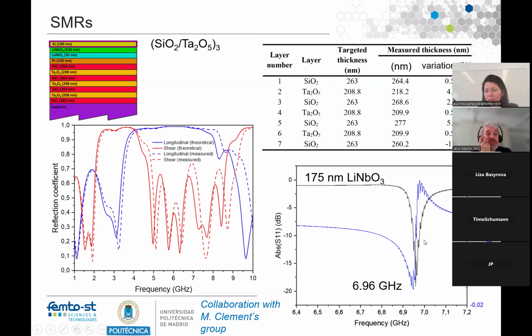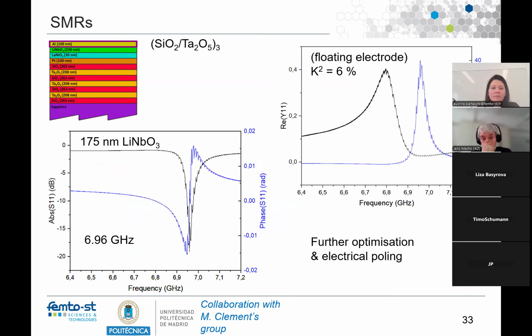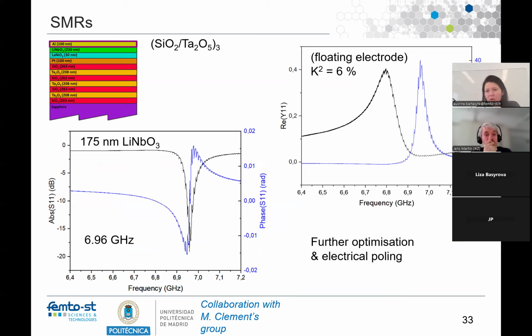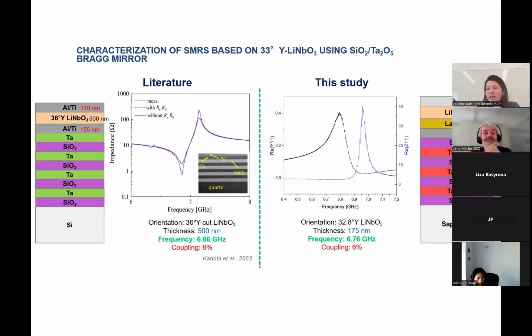And then we see these small ripples on the side. So the mirror is probably not working perfectly, but we had a nice resonance at 7 gigahertz. Then we used just a floating electrode and measured a coupling of about 6%, more or less. The signal is maybe a little bit noisy. To compare if it's good or bad, the only reference I have is again from the Kadota group. We did a very similar mirror, not tantalum oxide but tantalum silicon dioxide, with 500 nanometer lithium niobate Y36 cut. It's a single crystalline polished film with aluminum titanium electrodes. We were almost exactly at the same frequency as mine, but we had 8% coupling.